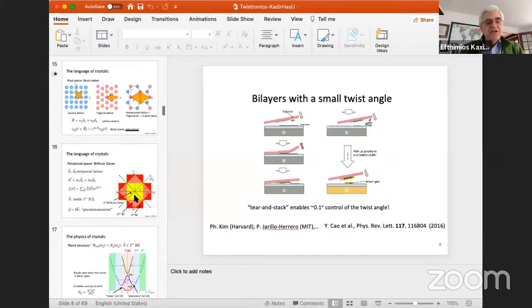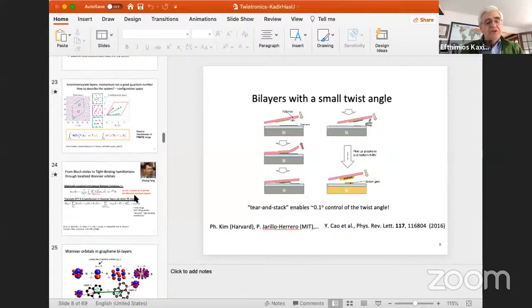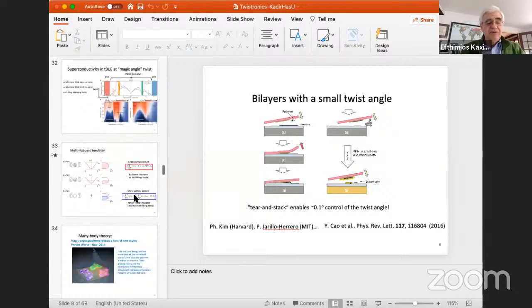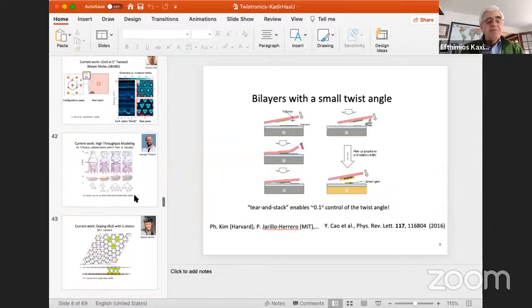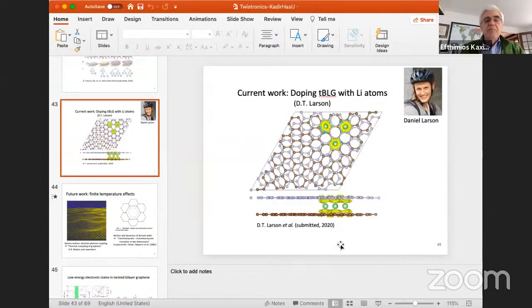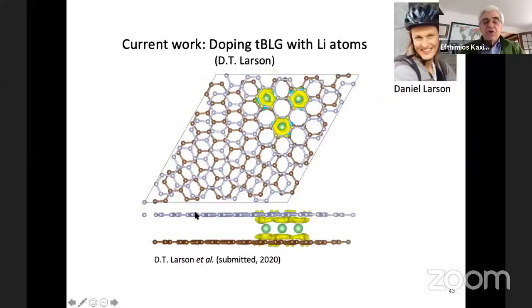And again, if you permit me to share my screen for a second, I'll show you a picture of what I have in mind. So graphene itself, as I mentioned, is a very stiff and strong lattice, very hard to include impurities. You can produce it in very pure form, and that's exactly what they're using. However, it is possible to insert atoms between the two graphene layers. And these are known as intercalants, intercalation. I'm showing you here two graphene layers, one on top, one on the bottom, with lithium atoms in between. That's actually how lithium batteries work. The anode is graphite, many layers of graphene, and you put lithium atoms inside, and that's when it's charged, and then you extract the lithium atoms, and then that's when it's discharged.